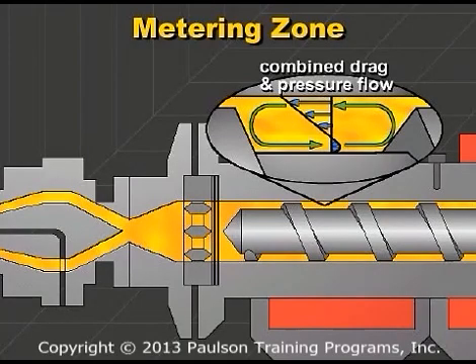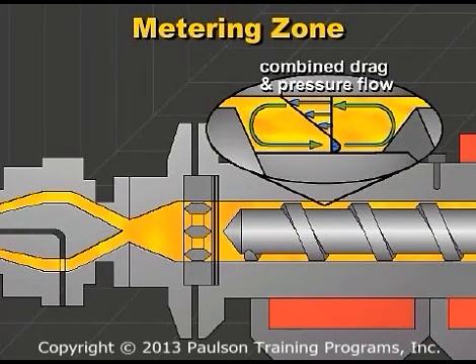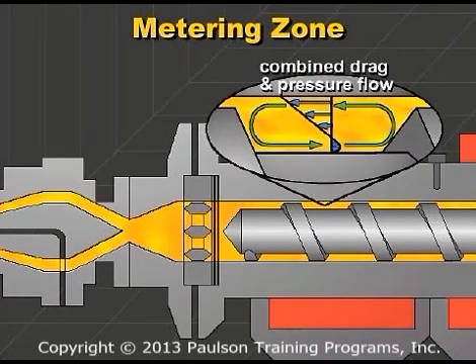The plastic rotates within the screw flight like this. The output of the extruder is reduced because some of the plastic — the pressure flow amount — is circulating and flowing away from the die.